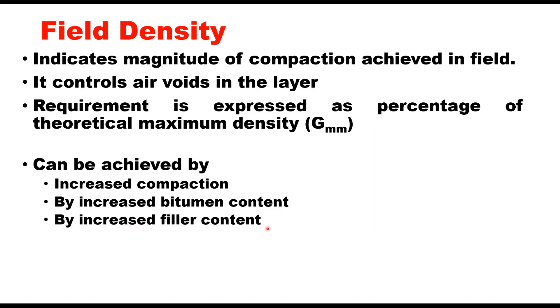However, it should be noted that increasing the binder content and the amount of dust in a mix can increase the density but do not necessarily have positive effect on performance of the mix. Increasing density due to increased compaction will increase shear resistance and therefore it will improve the performance of the layer.